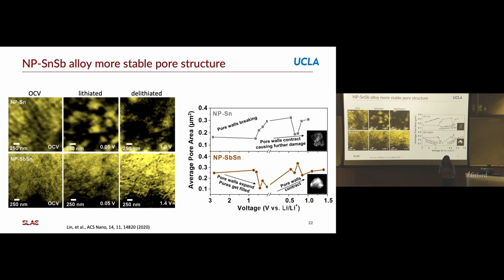So we think it's on the pore level that's the problem with the porous tin. The porous tin can't maintain that nanoporous structure. It's losing the nanoporosity, and the nanoporous tin antimony is actually able to preserve that.